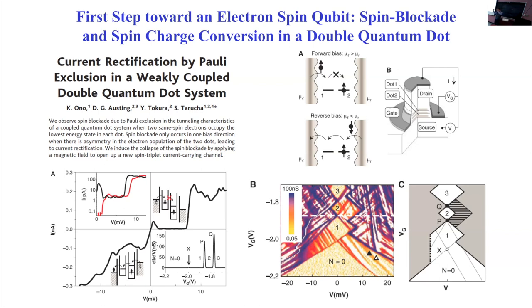Okay, so whether it's a singlet or a triplet, the charge distribution is roughly the same. So the energy splitting generally is pretty small. On the other hand, if you put both of those electrons in one of the quantum dots, if it is a singlet, both electrons can go into the ground orbital state. While if it is a triplet, one of the electrons has to go to the excited orbital state, right? Because of the Pauli principle. And so that gave you a large singlet-triplet splitting.